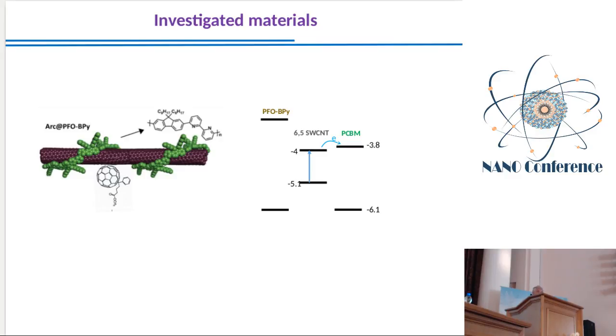Of course, these carbon nanotubes remain wrapped with this polymer. But this polymer does not have a big influence on electronic properties, because this polymer has a wide energy gap, much wider than carbon nanotubes. Therefore, it does not influence electronic properties strongly. And as I said, we also used this soluble fullerene derivative, PCBM, and these fullerene derivatives attach to the carbon nanotubes. So now we have such a kind of electronic structure.